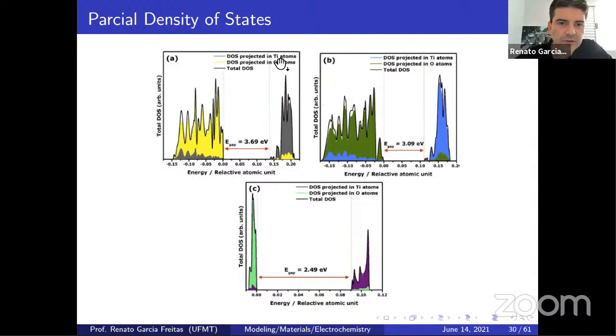Also, we observe the PDOS, where you can see here the higher oxygen contribution down there on the valence band. On the conduction band, higher titanium contribution, like in gray down here. In green, for the perfect one, for the oxygen displacement, we observed the oxygen, higher contribution of density of states in here, and the blue one, the titanium, increased the contribution for the conduction band. And from the nanotubes properly, we have, again, oxygen contribution, higher contribution of titanium, 2.49 band gap, and